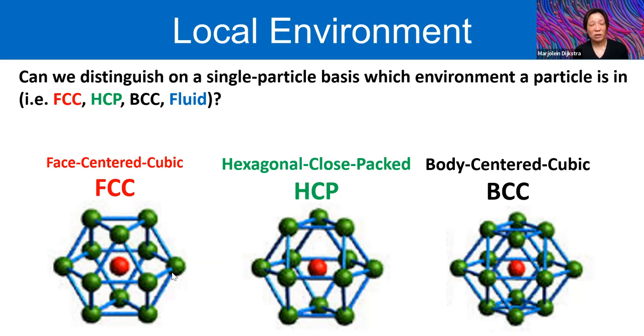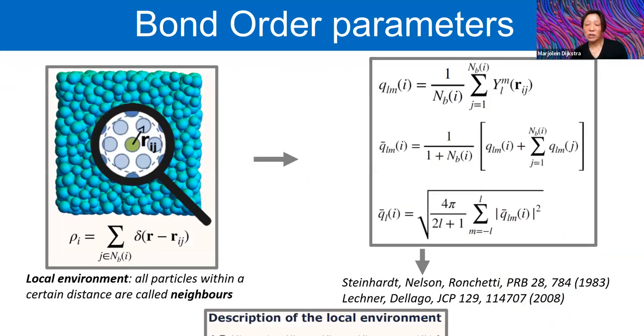So there's this six-fold ring around the central particle. In the case of the FCC and HCP phase, there's a triangle set of particles at the bottom and at the top. And only in the FCC and HCP, this triangle set of particles at the top is oriented in the opposite direction. While in the body-centered cubic crystal phase, this triangle set of particles is replaced by a square set of particles. So you need an extremely good order parameter that can distinguish these subtle differences in the environment. So for that, we use the so-called bond order parameters that were already introduced by Steinhardt, Nelson, and Ronchetti.